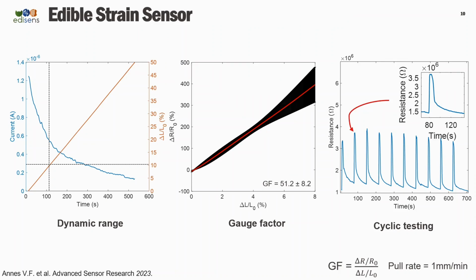And here is an analysis of the strain sensing results. First, we analyzed the dynamic range. So we want to focus on this part of the curve, at lower strain from 0 to 8. As you can see here, this is the strain. So maximum 10, where we have pretty much linear behavior. And then we analyzed it many times with different samples, achieving a gauge factor which is comparable to the state of the art, and a very linear curve. Also quite repeatable, as you can see here.